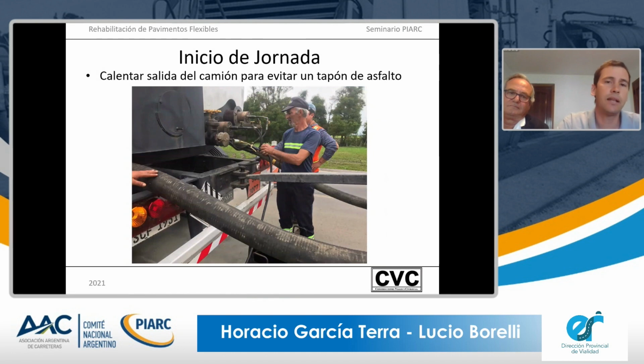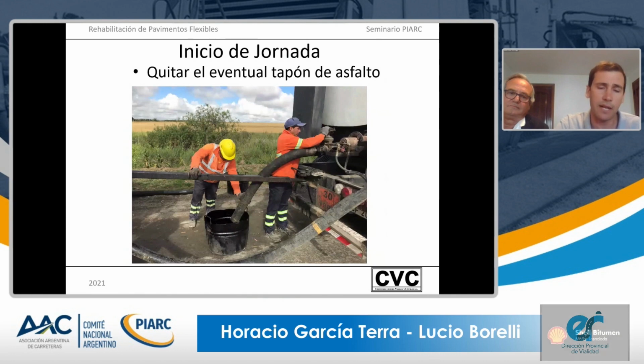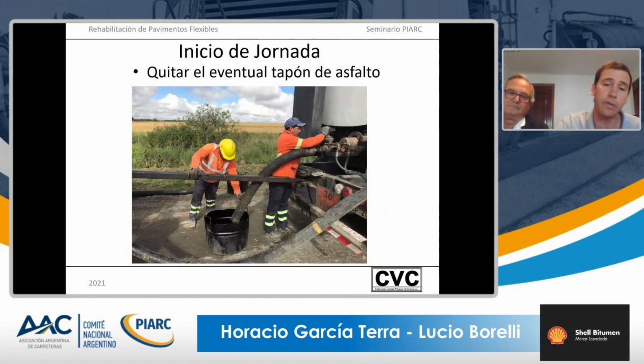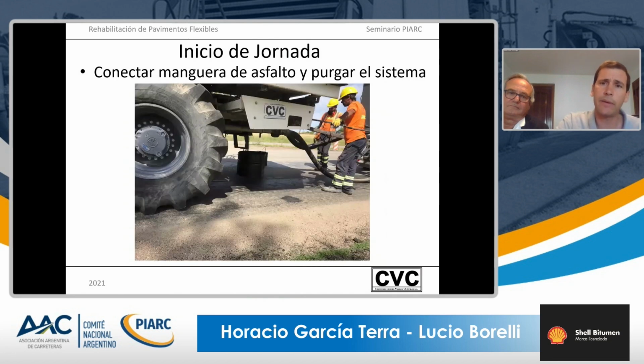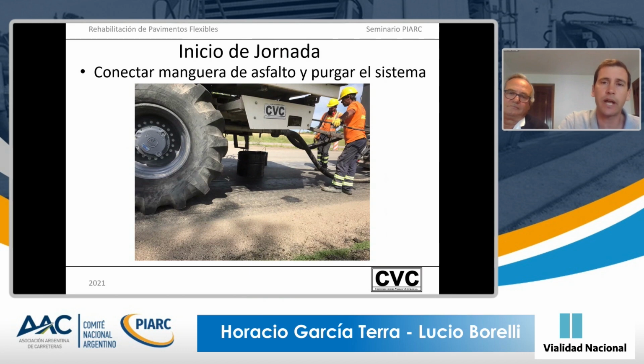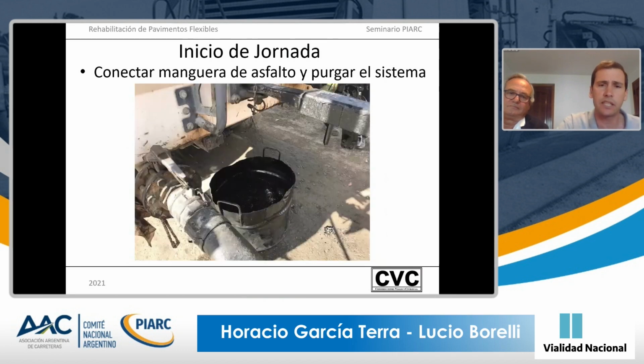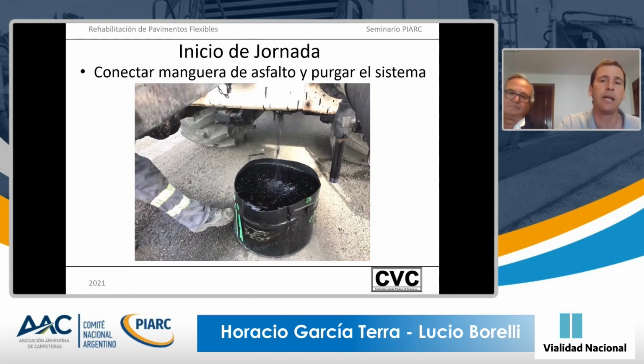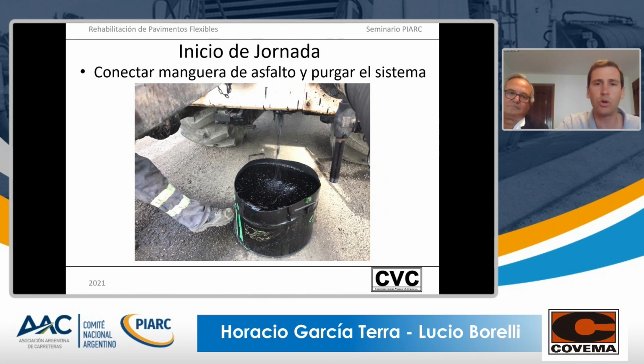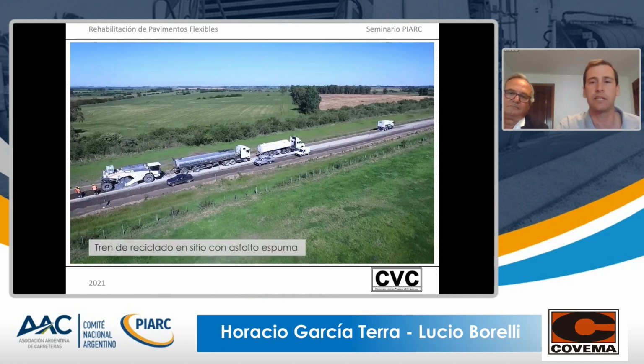And then we heat the outlet of the asphalt truck hose, and we need to make sure that we take out the stopper there, the plug that is there. Once we remove the asphalt plug, we connect the asphalt hose to the recycler, and we do an air purge until we have a constant flow of foam through the central nozzle, and that's when we can start recycling.